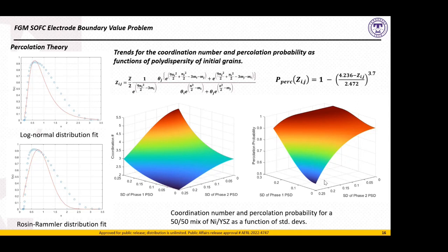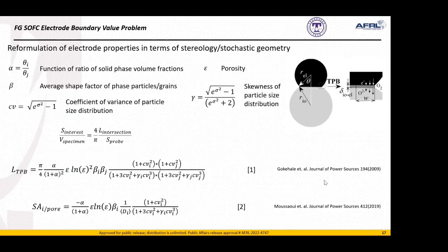Now, where this is important, again, the percolation probabilities define the critical composition and size distribution at which conduction can take place. Now, previously in the literature, as we move forward in applying this to the properties that are relevant for the electrochemistry, the length of the triple phase boundary, and again on the right-hand side you see here a schematic of the triple phase boundary, using relations from stochastic geometry in previous papers.